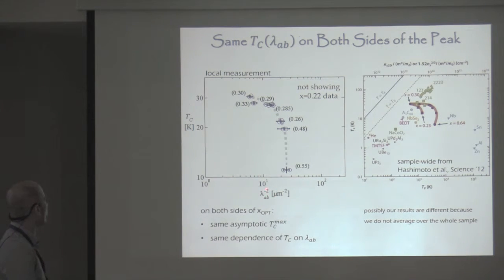This axis gives you 1 over the penetration depth squared. So this tells you something about the superfluid density. And this is TC. And this is all of our samples. You see that they sit on one curve that doesn't care what side of the transition you are. This is very different from the earlier measurement where there were 2 branches. And this could be insignificant, but it could be significant because it means, for example, that if there's some ultimate TC that you can get to, then it's the same for both underdoped and overdoped. You can see that the power is the same. I can't tell you what the power is because we don't have enough points.